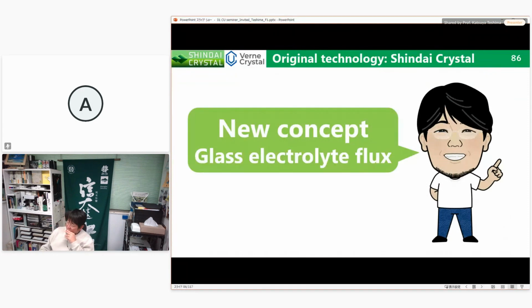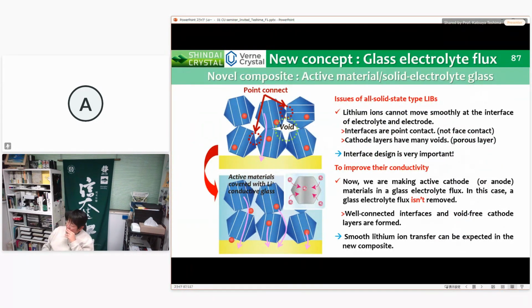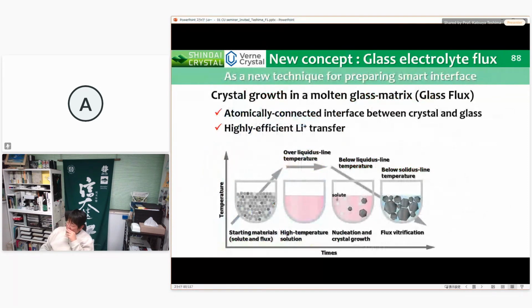Let me briefly introduce a new concept, glass electrolyte flux. This is a new concept in the glass electrolyte flux method. Using this technique, well-connected interfaces and void-free cathode layers can be fabricated, so smooth lithium-ion transfer can be expected. In this glass electrolyte flux method, active material crystals grow in the molten glass. As a result, an interface is formed between the atomically bonded active material and the solid electrolyte.